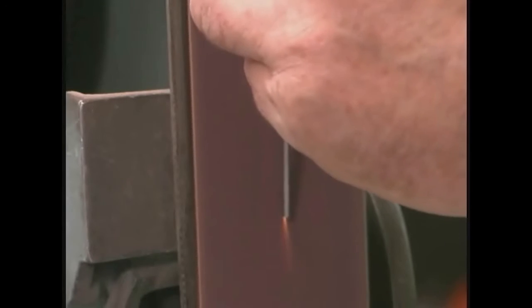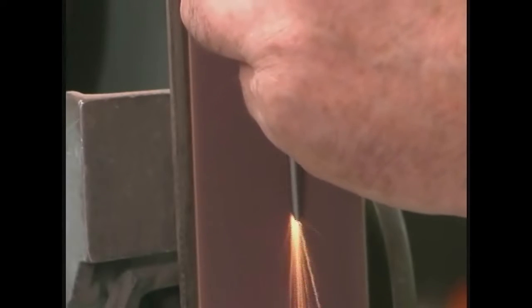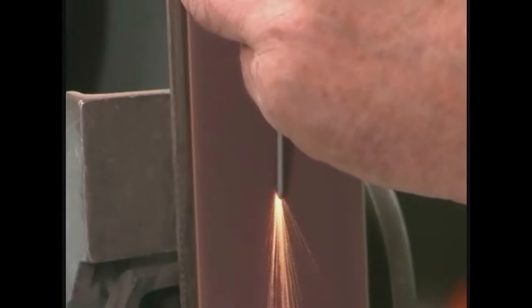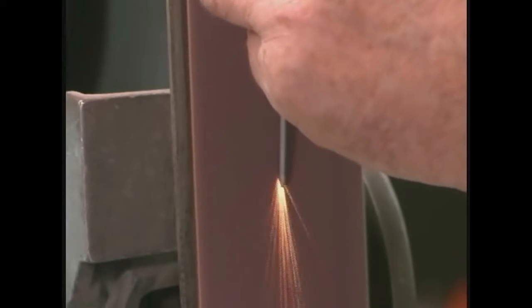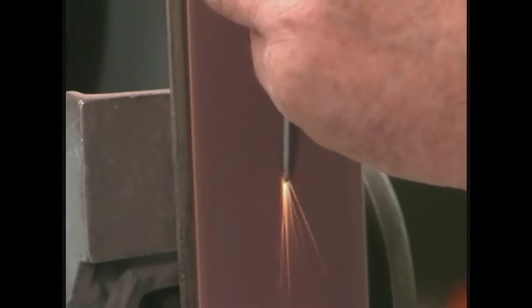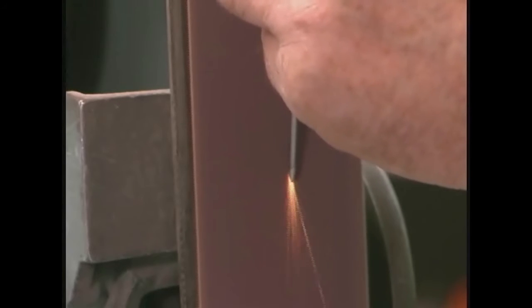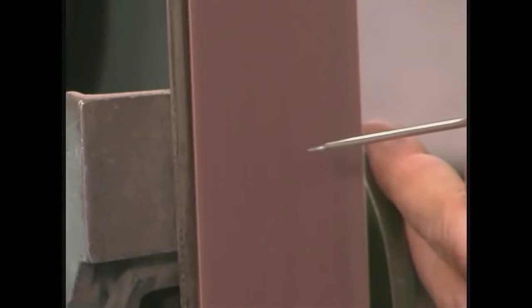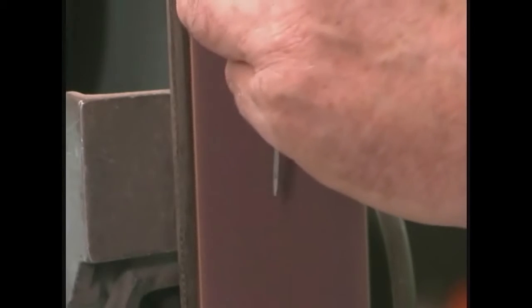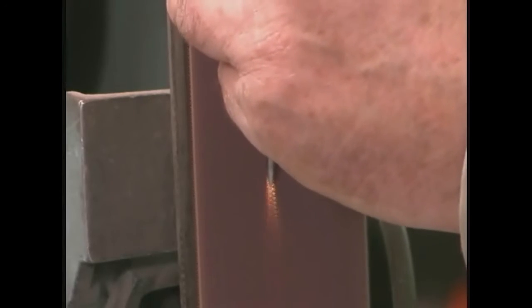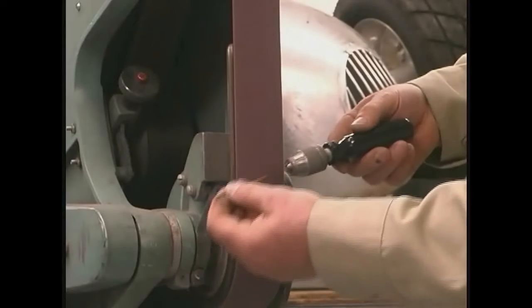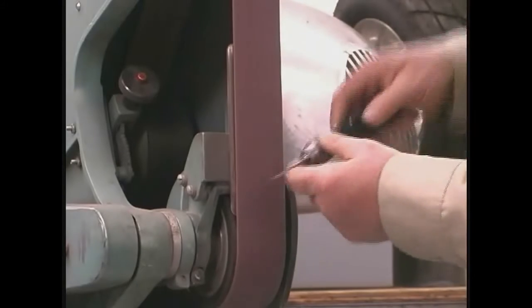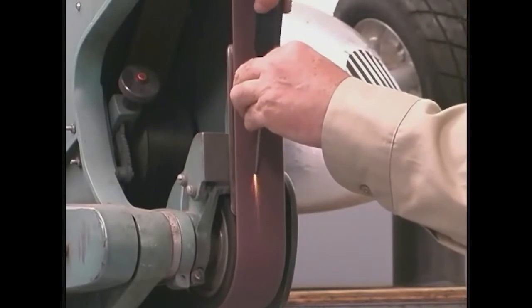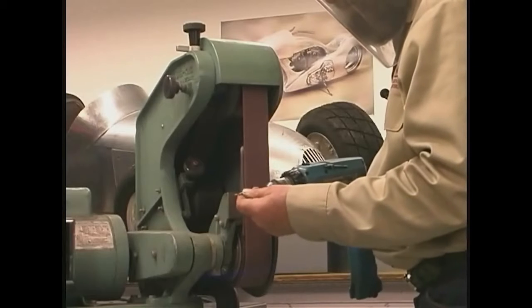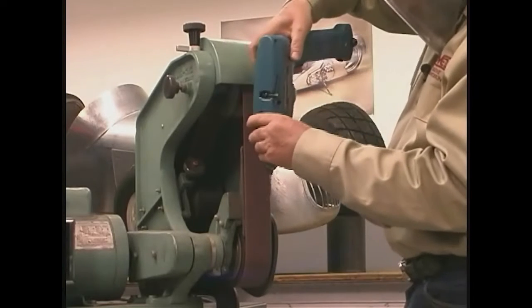The tungsten electrode is pointed by sanding or by grinding. For very sensitive work that must pass X-ray testing, it is recommended to use a dedicated belt or wheel used for tungsten electrodes only. If you're not doing sensitive mil-spec work, you don't need to be quite so fussy on this point. If it's a pretty long tungsten, I can hold it in my fingers and rotate it at a steady rate to sand the tip. If the electrode is short, it's better to hold it in a pin vise. Another very convenient way to point electrodes is to use a cordless electric drill.